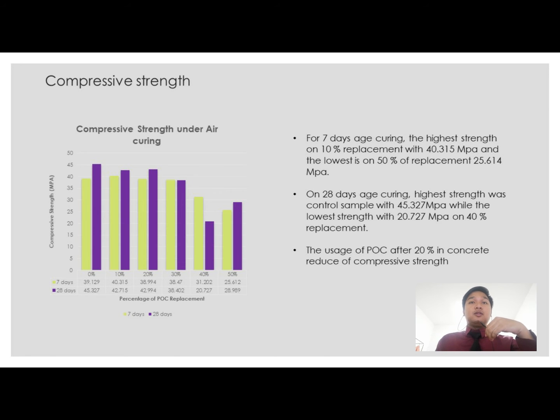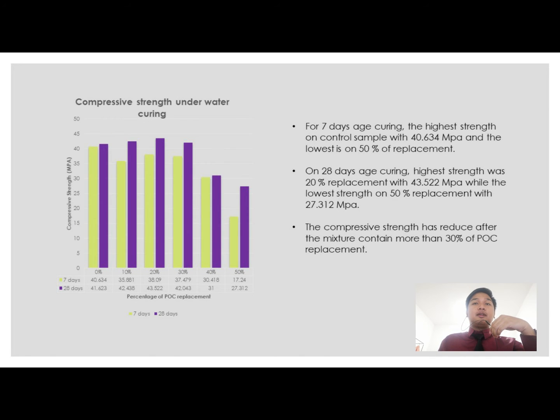Compressive strength under water curing. For 7 days water curing, the highest strength is the control sample with 40.634 MPa, and the lowest is at 50% replacement. For the 28 days of water curing, the highest strength is at 20% replacement with 43.522 MPa, while the lowest strength is at 50% replacement with 27.312 MPa. The compressive strength is reduced after the mixture contains more than 30% of POC in the concrete.